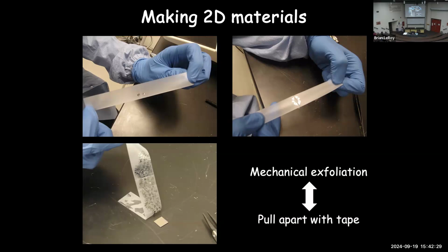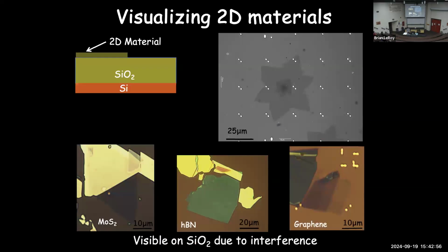Once you've done the process like 40 times, you have very thin pieces on the tape, and then you can press them onto a piece of silicon or a piece of plastic or whatever substrate you would like to put them onto. After doing this, you have transferred these bulk materials onto the substrate. And the last thing, the trick that you need to do, is to go and identify these materials on the substrate. We are able to do that using basically thin film interference.